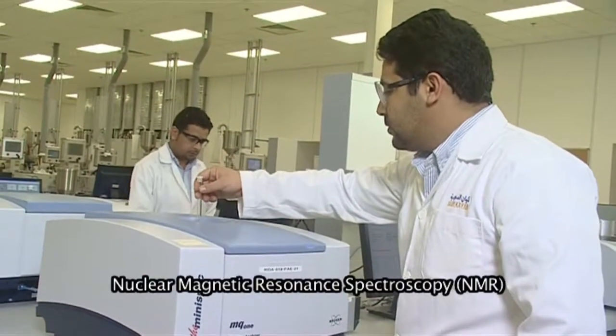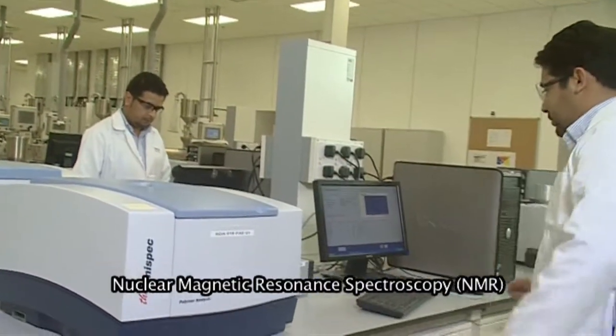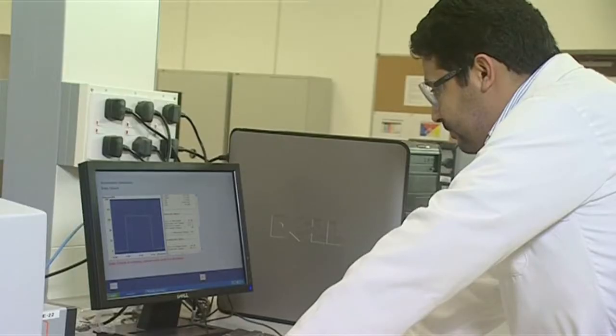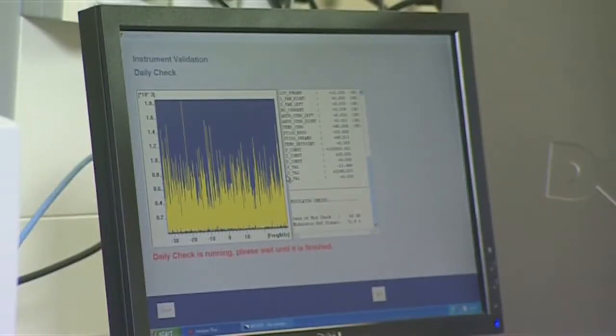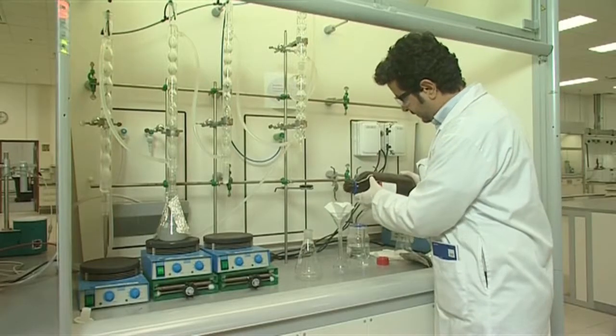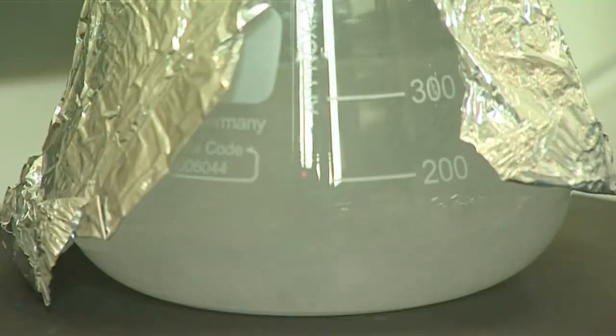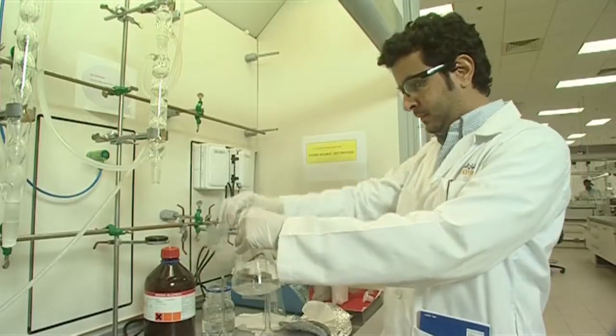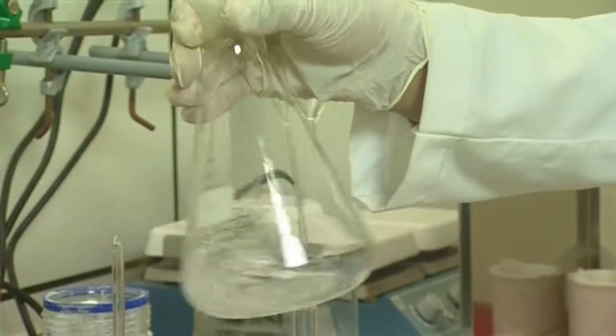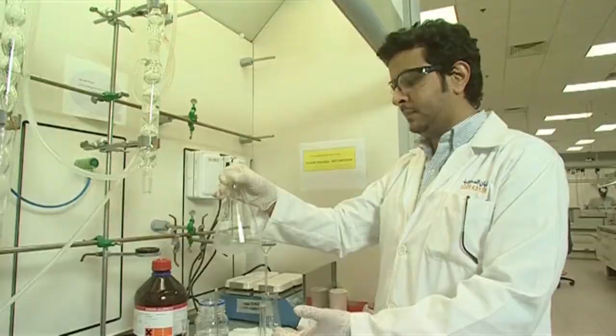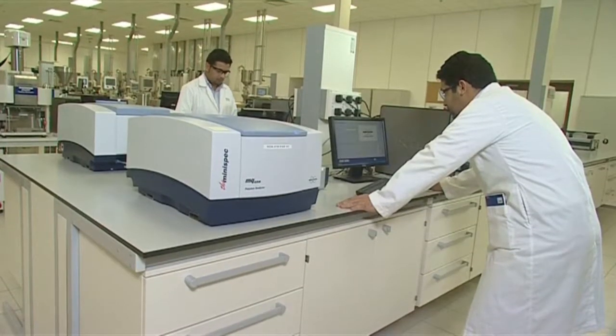Nuclear magnetic resonance spectroscopy is a preferred analytical tool for determining the atactic or amorphous polymer contribution in polypropylene. This test is traditionally performed by the chemical method, which takes around 5 hours and has to be performed carefully to avoid chemical hazards. The NMR method reduces the time as well as avoids the hazards related to traditional chemical method.